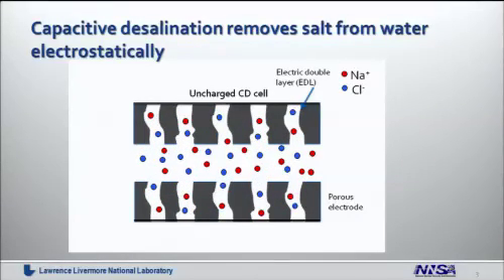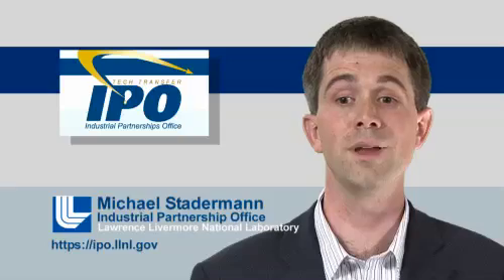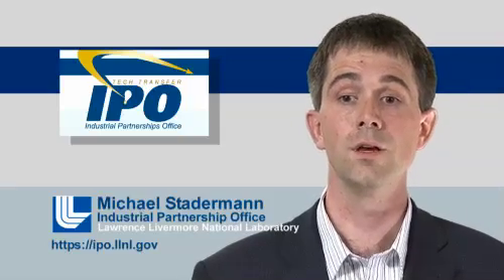The stream that we now have between the electrodes is called brine — it is enriched and has about twice the concentration of what we initially fed in. We can remove, depending on the salt concentration of the feed stream, either all of the salt or just some of the salt. The energy used to charge up the cell is stored on the electrodes as a capacitor, so almost all of it can be recovered, which makes this a very attractive method for desalinating water.